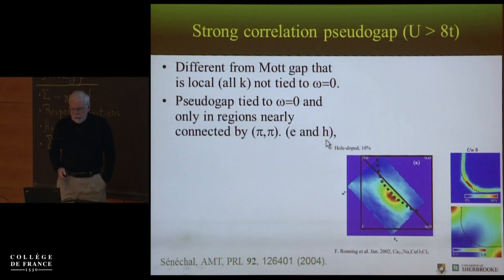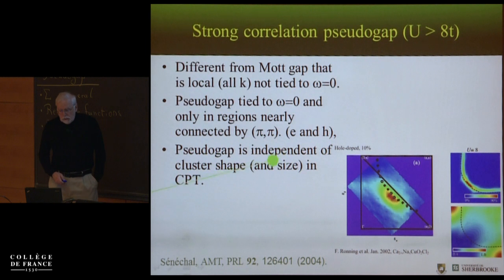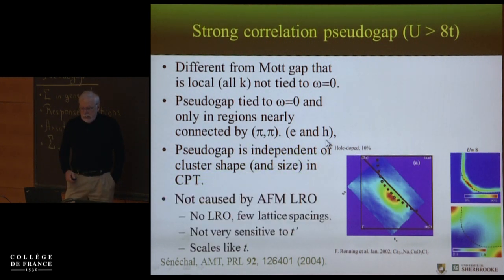On the other hand, there's a different object, the pseudogap, that is close to omega equals 0, this depression in density of states, and only in regions that are nearly connected by (pi,pi). The pseudogap is independent of cluster shape and size in these methods, and it's not caused by antiferromagnetic long-range order. It's not so sensitive to t prime, the next-nearest neighbor hopping, and it scales like hopping.